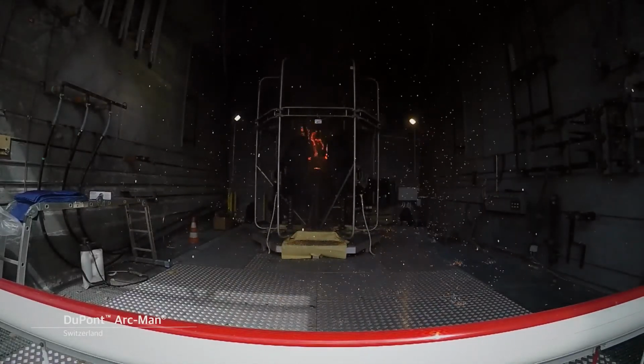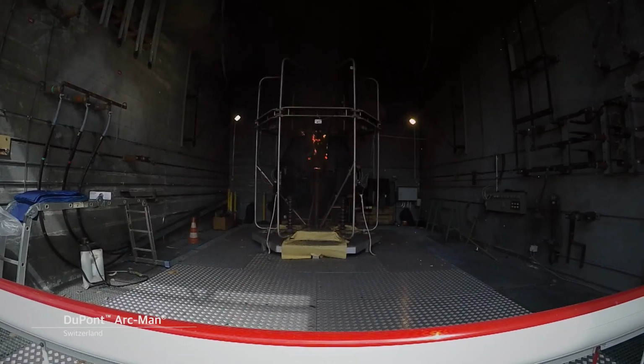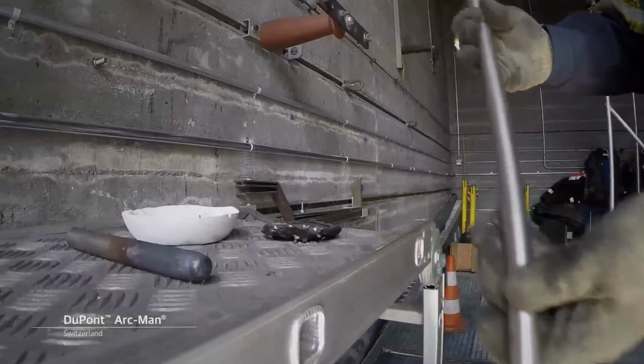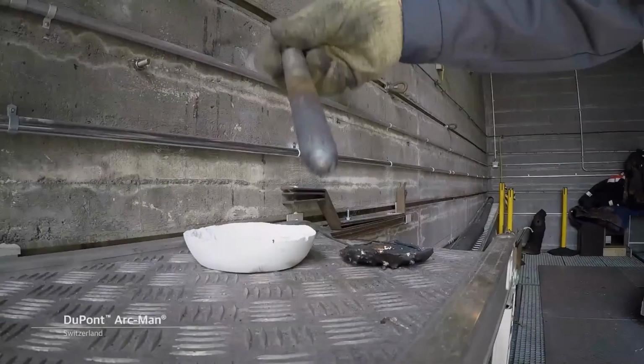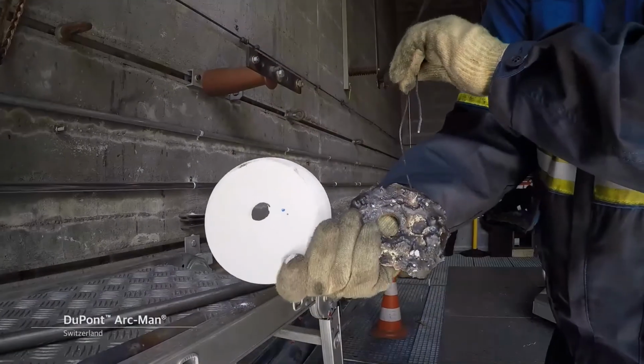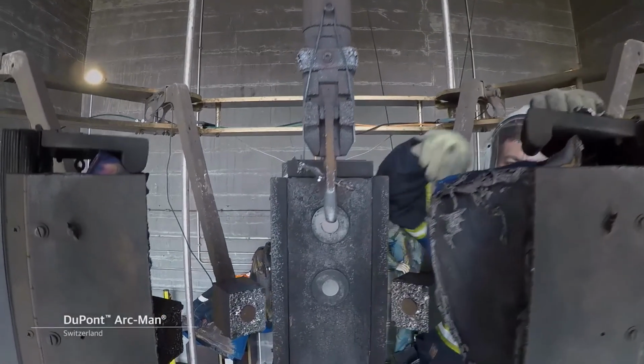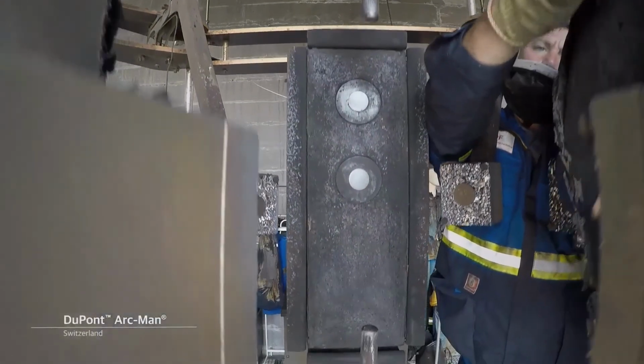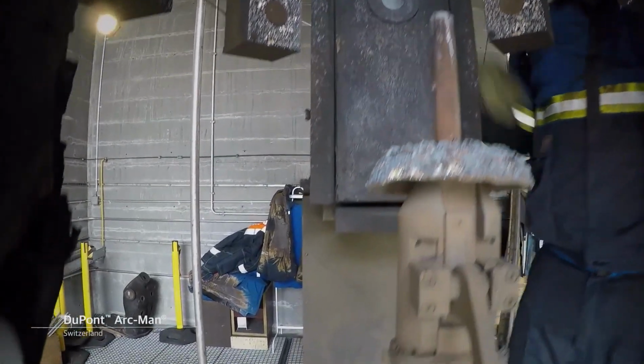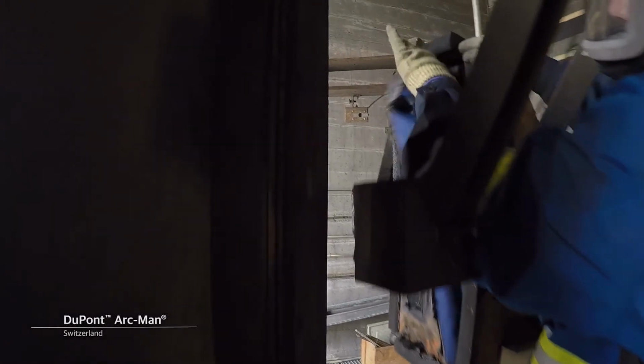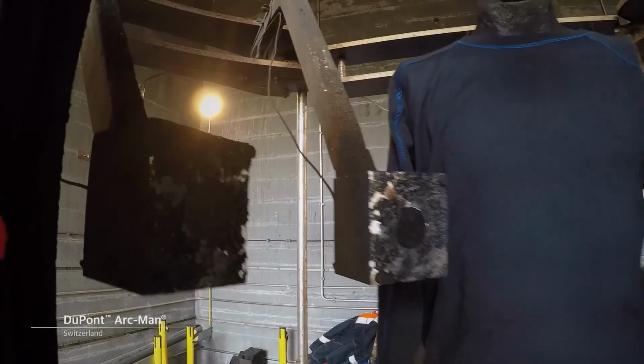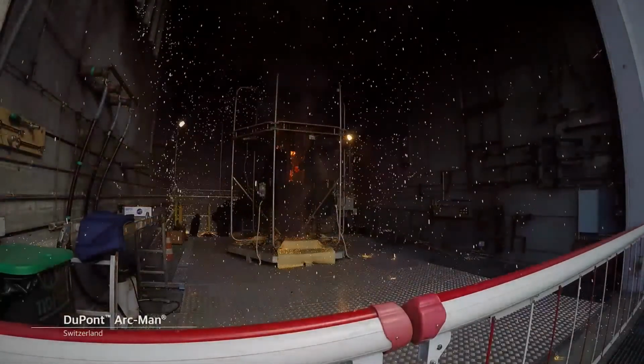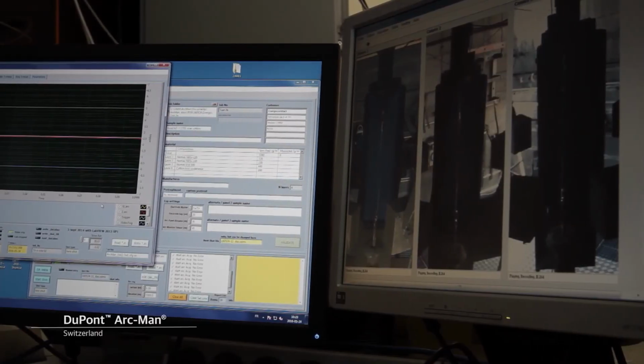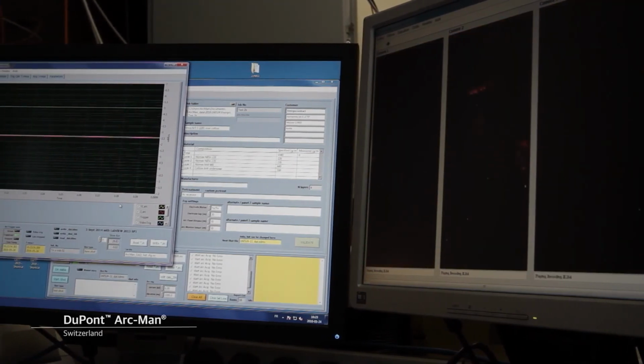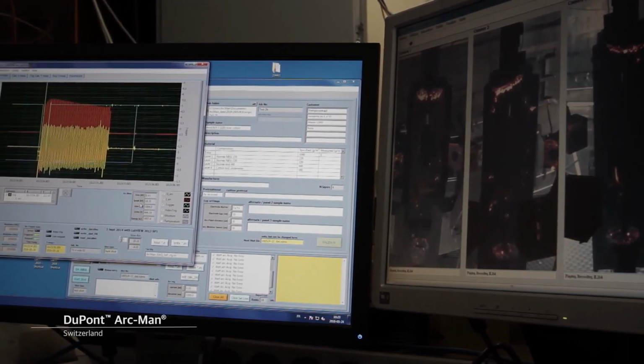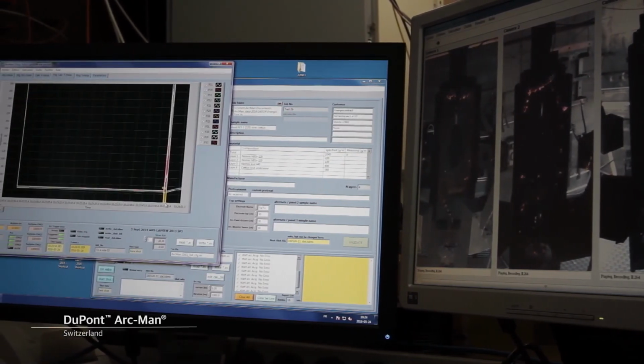The electrical arc is instantaneously ignited through the help of a 30 centimeter fuse wire laid across the gap between 2 stainless steel electrodes, which are positioned in the center of the test rig. The test voltage needs to be sufficient in order to maintain an electrical arc across the distance between the electrodes during the tests. This is typically between 2 and 4 kilovolts. The voltage drop along this arc is typically between 400 and 700 volts. The duration of the arc will vary from test shot to test shot, from 120 milliseconds to 2 seconds, in order to achieve the required incident arc energy.